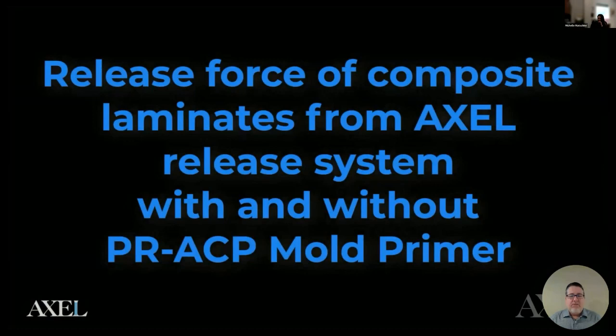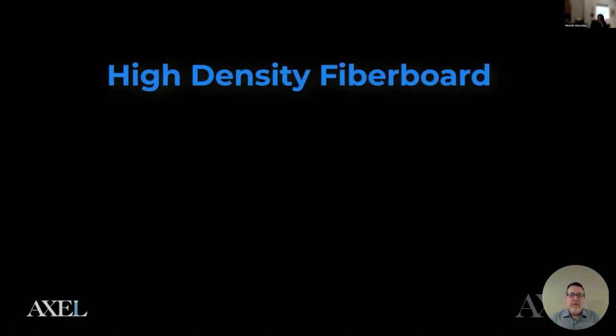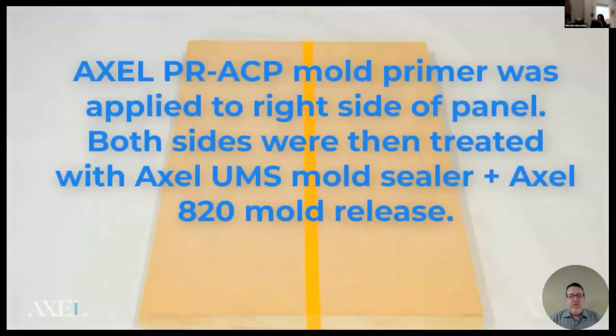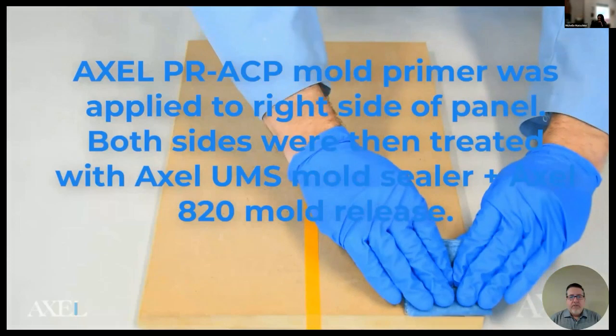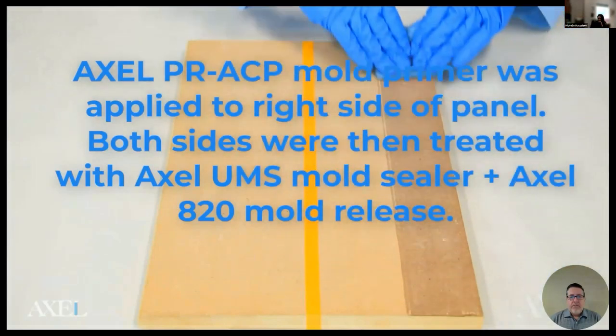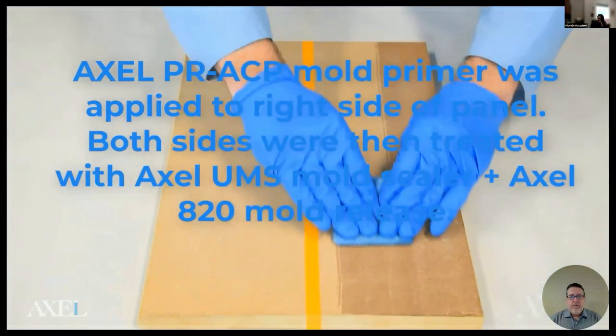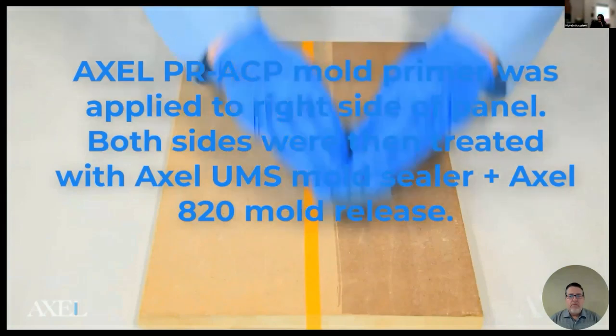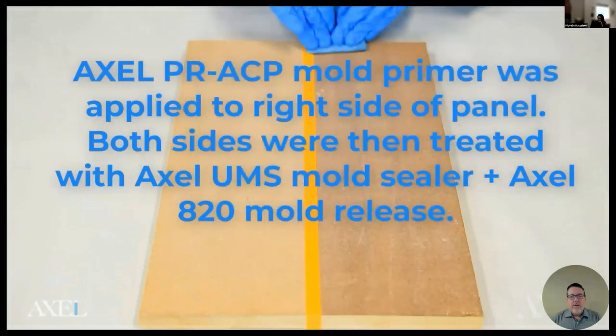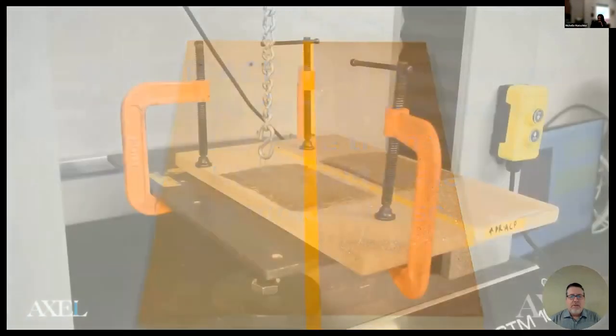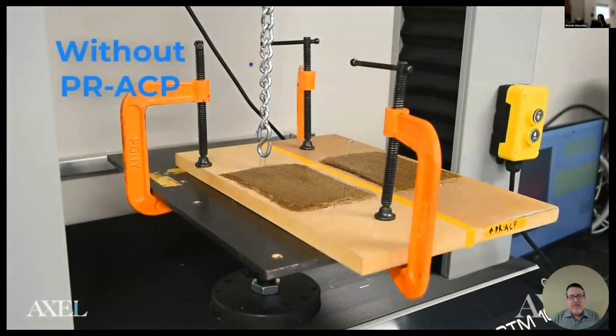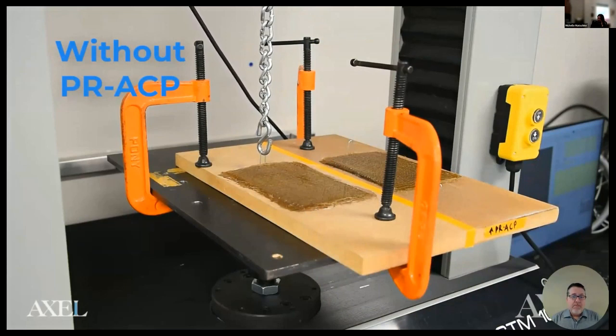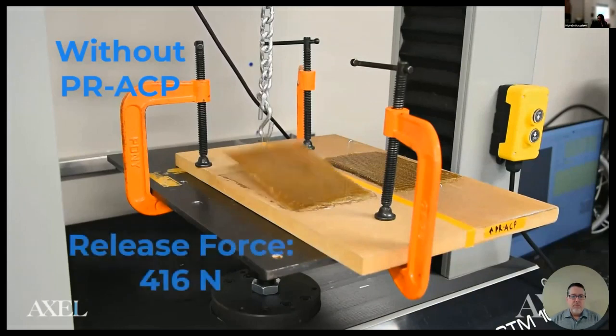And there's a dramatic difference in the release force, over 400 newtons for the side without primer and just 5 for the side with. So here you'll see just a quick application of the primer. The first coat, actually, I believe it's the first coat. And in total, when it goes to release, there's been a total of 5 coats applied to one side. You can see the difference of the finish on the right where the primer's been used. Both sides have 1 coat of sealer and 1 coat of mold release.